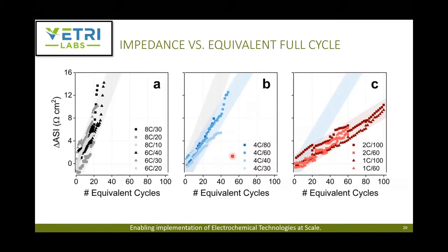And then they did another interesting study. They took these impedance curves and extracted equivalent full cycles. Say, for example, you did it at 40% SOC, and based on the capacity value, if you did 2.5 cycles of that 40% SOC, they considered it as one full 100% SOC cycle. That's what they call equivalent full cycle. So when you do the analysis that way,